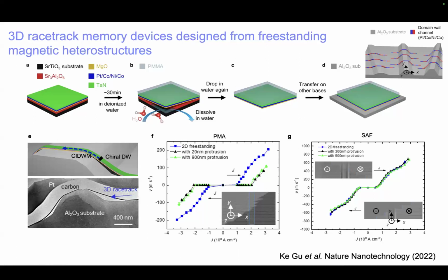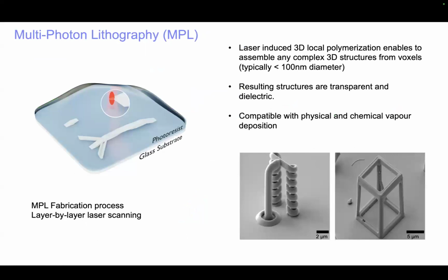And we found that the domain walls could be moved as efficiently, with the same velocities, in this racetrack, which has basically been a freestanding racetrack that we've gone through this process of dissolving this water-soluble oxide layer and then transferring this 10 nanometer thick racetrack film onto a substrate. So I think this is quite remarkable. And the TEM image shows a hillock which is 0.3 microns tall, but we actually made them up to 1 micron tall. Finally, let me show another method for 3D fabrication.